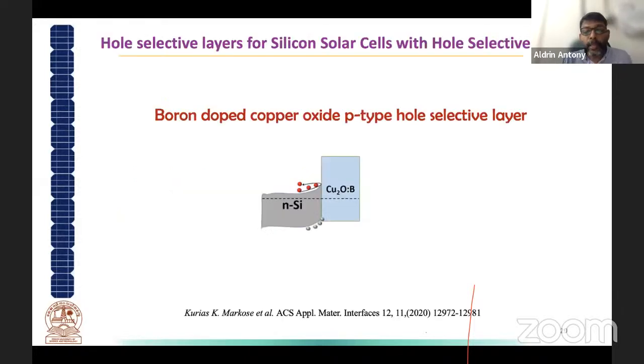in solar cells. The first one is what we have recently developed, which we call boron doped copper oxide as a p-type hole selective layer. Normally, we have made copper oxide into a p-type material, Cu2O, which is p-type in nature. When it comes in contact with crystalline silicon, this forms a band bending up, like what I was saying, blocking all the electrons and allowing only the holes to move in this direction.